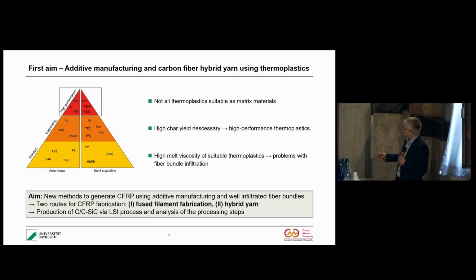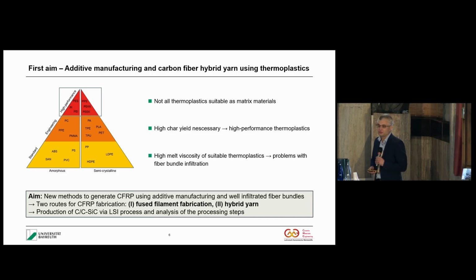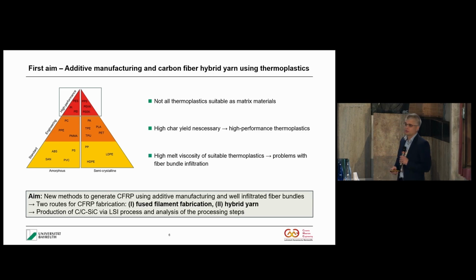And also, a disadvantage, as I was saying, is the high melt viscosity. Usually, if you think about thermoplastics for these kinds of applications, you end up with so-called high-performance thermoplastics, for example polyether ether ketone or polyether ketone. These are polymers that have a ring as a backbone, and that's why they have a high char yield after pyrolysis, which is the main reason.